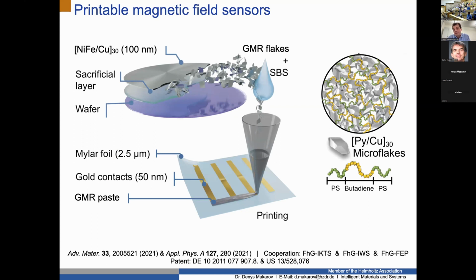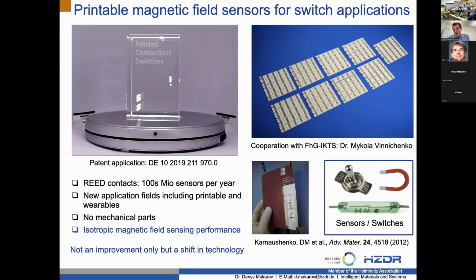And here starts already a lot of interesting chemistry and material science, because the binder has to be appropriately adjusted in order to assure adhesion, of course, assure electrical percolation and processability of this material. In our case, we work, for example, with tri-block copolymers like SBS in this notation, which gives very interesting possibilities to put these devices even by printing to ultra-thin foils.